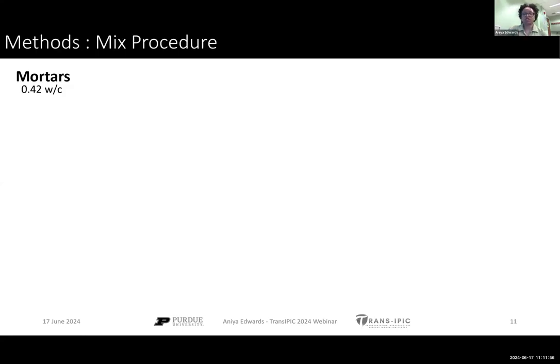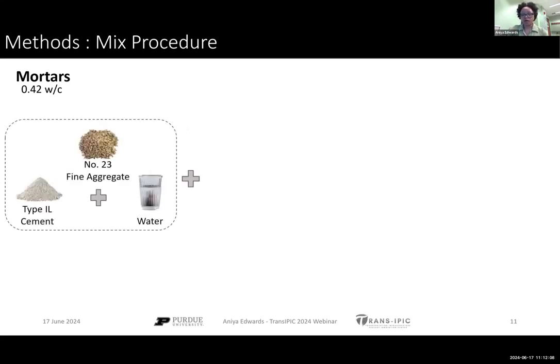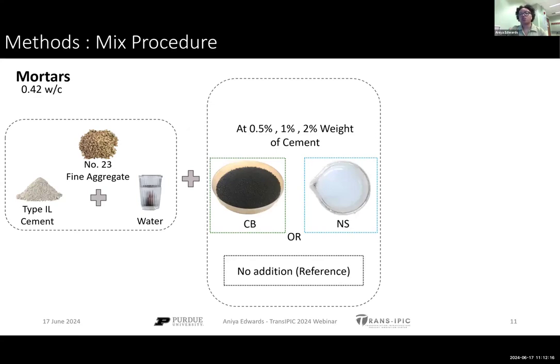So the methods and mix procedures. What I will be showing to you today is the mortars that we're going to be mixing at 0.42 water to cement ratio. We're also mixing paste and concretes, but I really want to focus on the mortars for now. So the mortars that we'll be mixing will be mixed with type 1L cement, number 23 fine aggregate, and water. And then we'll also be creating 3 kinds of mixes. We're going to be using either carbon black or nanosilica at 0.5, 1, and 2% by weight of cementitious material, or no addition of nanomaterial. So that's going to be our reference sample.